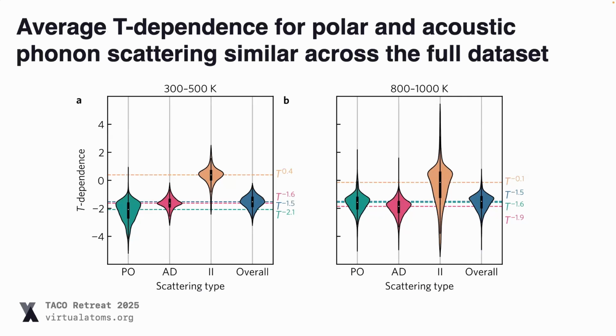And this is a summary of the results. If you look at the left side, this is at 300 to 500 Kelvin. These are violin plots, so they show you the density of your values, and on the y-axis it's the temperature dependence. You can see that if we look at the distribution of polar optical and acoustic deformation potential scattering, these essentially completely overlap. So if you measure a material and you see a T to the -3/2 temperature dependence, there's really no way that you can assign that to polar optical or deformation potential. And this, I think, agrees nicely with what we've been showing before.